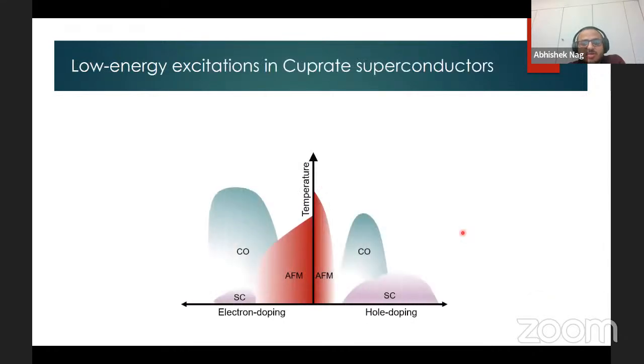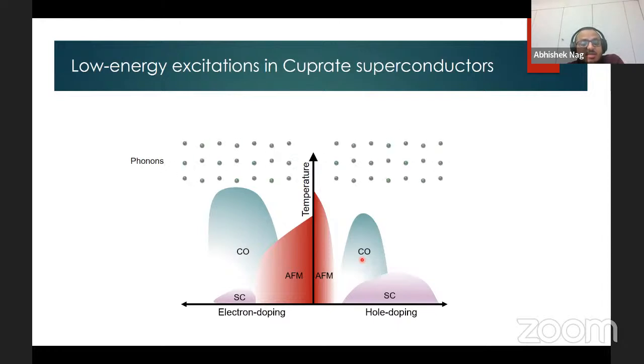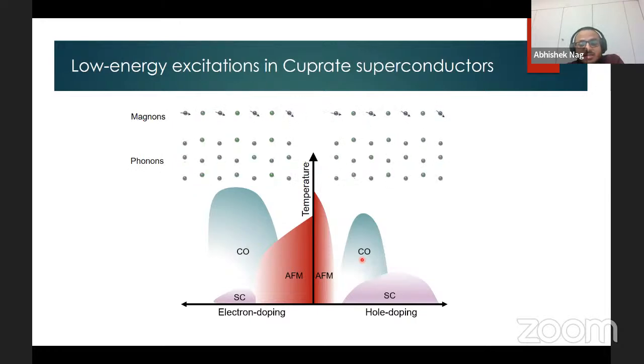So let's begin with the well-known cuprate phase diagram that originates from doping of electrons or holes into the antiferromagnetic charge transfer insulators. As you can see, despite subtle differences in the various orders, there is also a significant amount of similarity between the electron and the hole doped sides. To understand the different phenomena in this cuprate phase diagram and eventually the origin of superconductivity, scientists are looking for low energy bosonic excitations that can couple to the charge carriers. The primary bosonic excitations identified to play a significant role in the pairing mechanism are the phonons, or the lattice vibrations, or the magnons, the spin excitations.